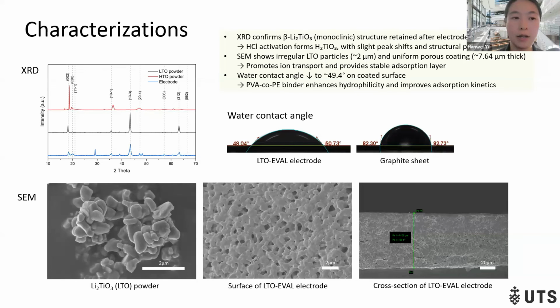In the characterization, the XRD confirms the LTO structure, and the SEM image shows the LTO particles and the uniform polymer coating of the LTO layer on the AC electrode on the graphite sheet. And the water contact angle test shows that the incorporation of PVA-co-PE binder enhances the hydrophilicity and improves the adsorption kinetics.